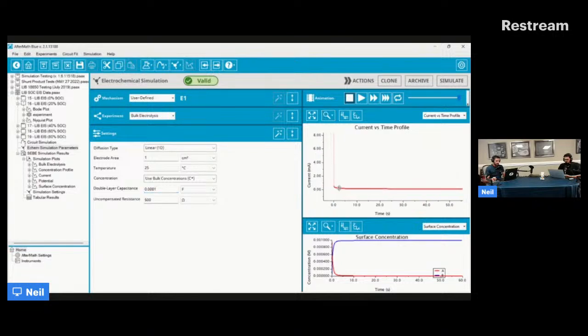So the faint red line is before, with basically no time constant. It's zero, it decays immediately. Look here, same diffusion. Now I could adjust the diffusion coefficient too, because that might be occurring. But basically, look, this is, for example, a hydrogel. This has a higher resistance than before and maybe a higher capacitance. Well, look at that. It's a higher baseline.